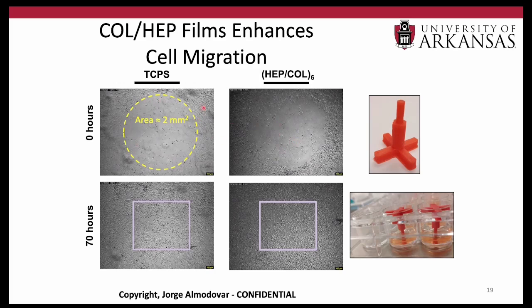And what we saw is that in the control surfaces, after 70 hours, we have cells that go there, but they don't completely cover the entire surface, versus our coatings, where we see a complete coverage of the empty area.